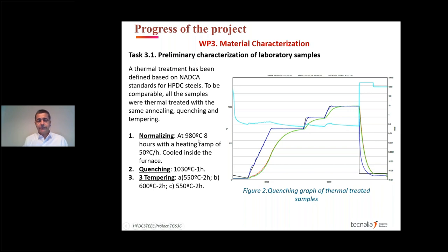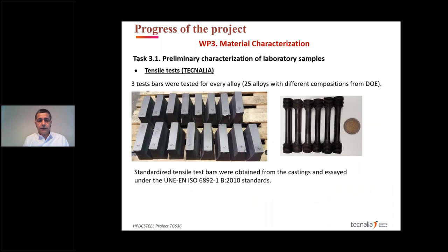So we establish, based on NADCA recommendations, normalizing temperatures of about 980 degrees, a quenching temperature of 1030 degrees, which is slightly higher than the standard one, but we wanted to increase the austenization of the alloy, and a tempering temperature of 550 degrees. So this was something to be comparable with all the 25 alloys. So here we have some of the test bars, minimum 3 test bars were employed.